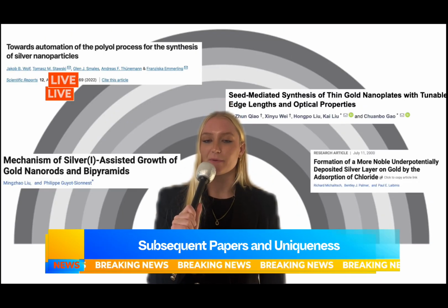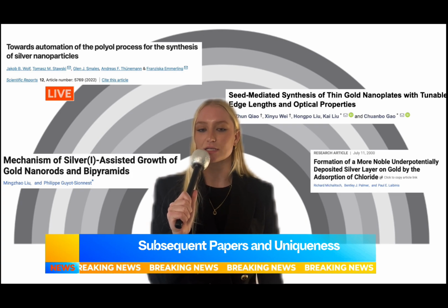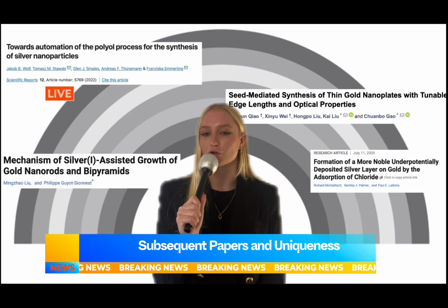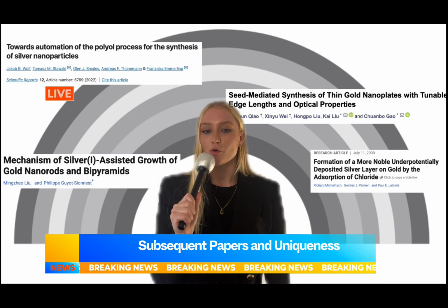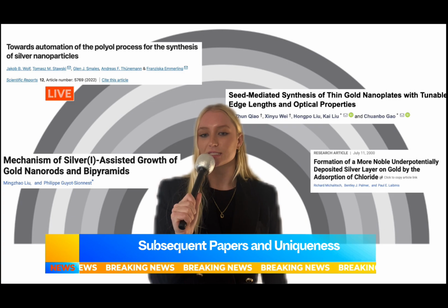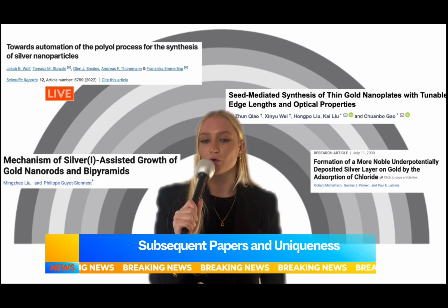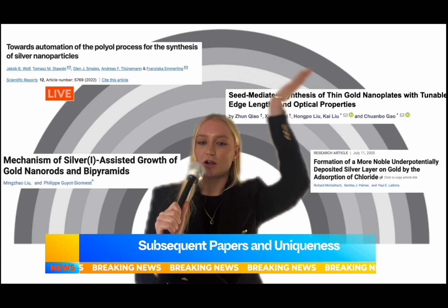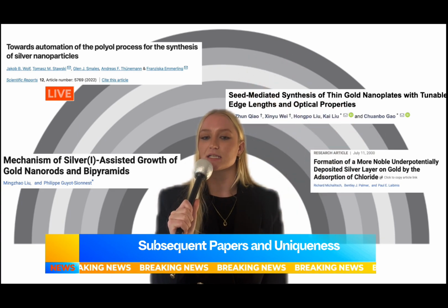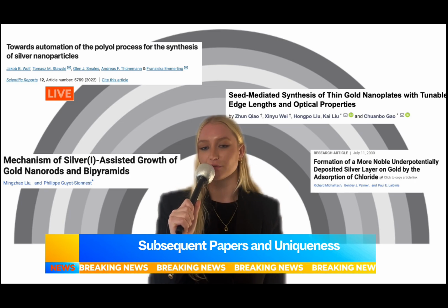The authors conclude the same effects of trace halides in the presence of silver ions in seed-mediated colloidal synthesis, as were studied on electrode surfaces in electrochemical cells in this paper. Research by Gao has involved sulfide ligands in halide-free seed-mediated synthesis. Sulfide controls reduction kinetics but also adsorbs onto facets, reducing gold nanoparticle thickness. Research by Wolf and colleagues further explores halide-free synthesis and shows that nanoparticle size is related to a lower ratio of the surfactant to silver ions.